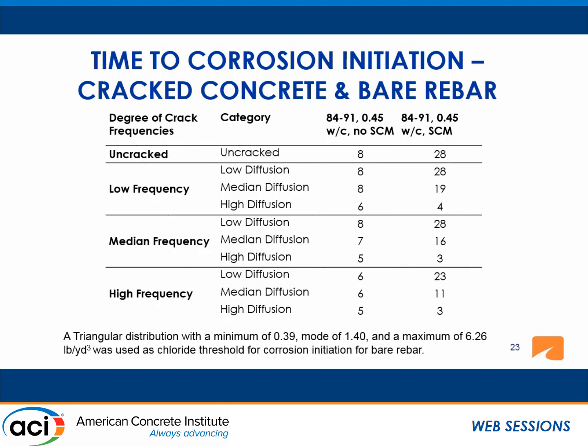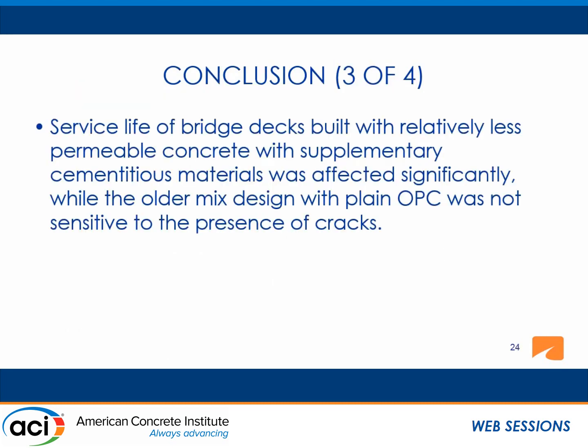When you look at the supplementary cementitious materials, it performed really well when there are no cracks. But the service life seems to be much more sensitive to the presence of cracks for the supplementary cementitious materials. We think this could be because of the pore structure and the significantly higher moisture saturation in the deck itself. So the inference is, for a deck with no supplementary cementitious materials, it is porous enough that the cracks don't seem to make a lot of difference. But when you have really good quality concrete, the cracks seem to make a difference in the time to corrosion initiation. And that's our third conclusion.